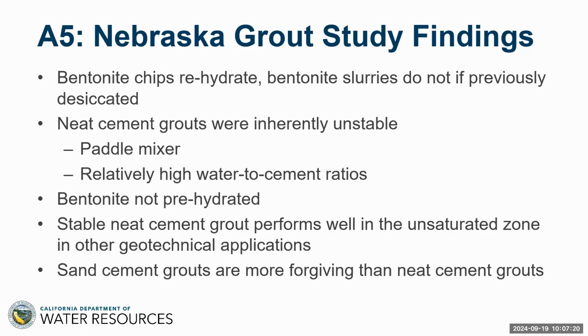We know from other geotechnical applications that stable, neat cement grout mixed in a colloidal mixer performs perfectly well in the unsaturated zones. What we had in Nebraska was a paddle mixer and relatively high water cement ratios. So between these two factors, the fact that the grouts that were produced seemed to be unstable and bled unacceptably is wholly logical. Another really important thing was that sand cement grouts are more forgiving than neat cement grouts in terms of water cement ratios and so on.